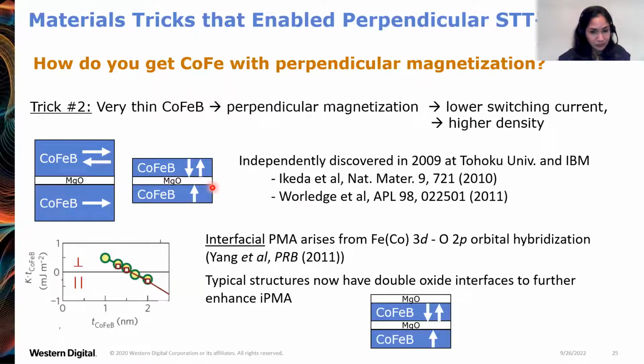As you thin down, at this interface of the cobalt iron boron and the MgO, there's a perpendicular magnetic anisotropy generated at this interface from orbital hybridization between the iron and the oxygen atoms. And so this is an interfacial perpendicular magnetic anisotropy. You can see here, as you thin down the cobalt iron boron layer at about 1.5 nanometers, you get this crossover in anisotropy from in plane to perpendicular.